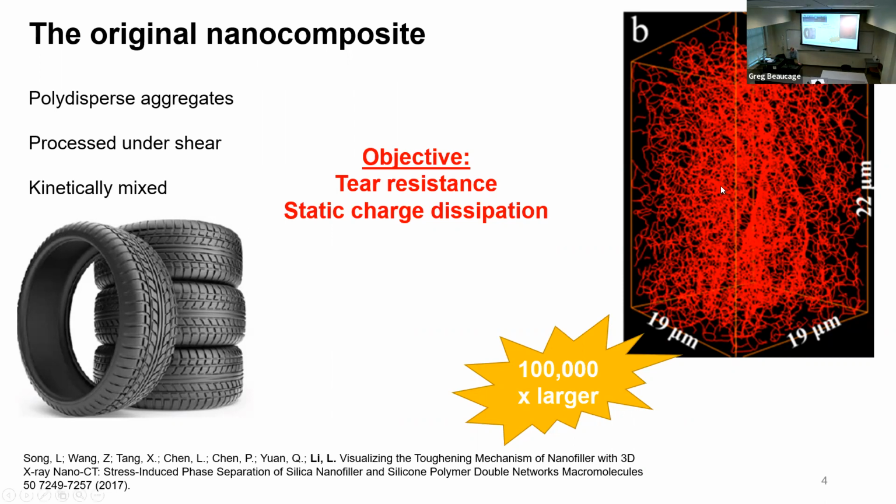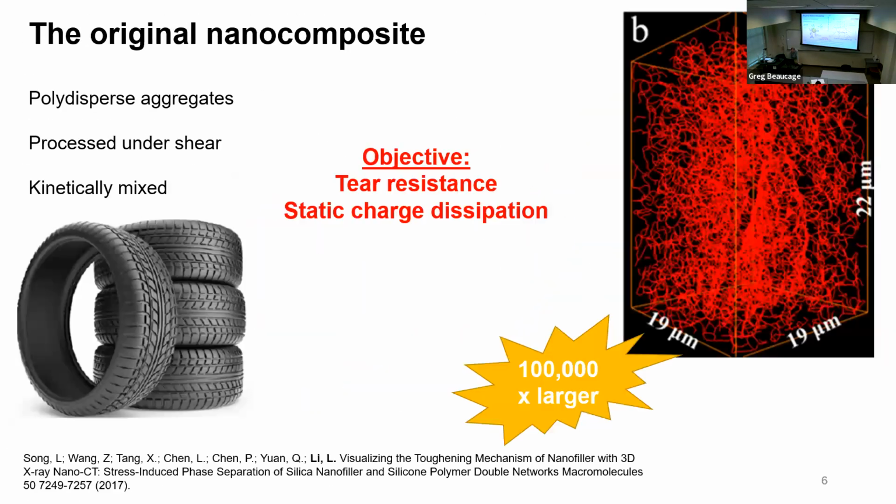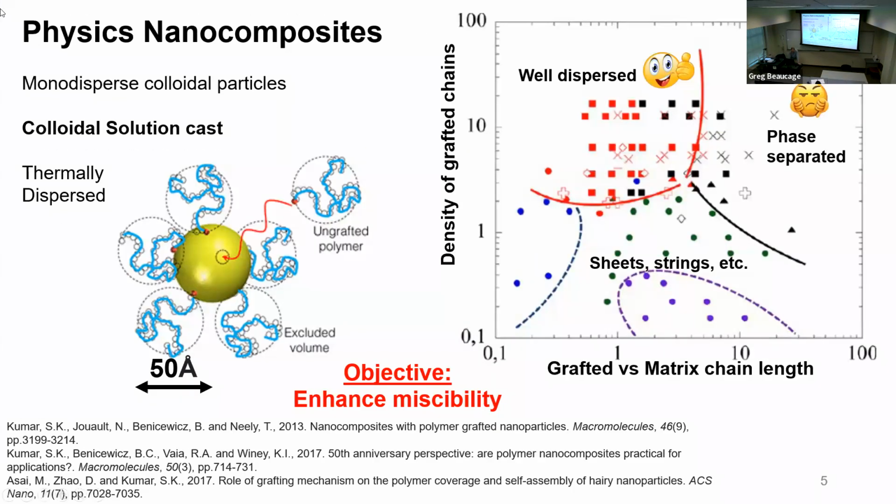So this is the kind of thing you want, you know, and this is kind of what people are doing, right? So you take a monodispersed spherical particle of silica, which you can make by a sol-gel synthesis using that same TEOS. You take that TEOS, put it into ethanol or into an ethanol-water mixture, then change the pH, and the TEOS will condense, produce water or ethanol, and then these perfect spherical particles will come out. That's called Stöber synthesis. It's been around since the 50s. So you can make perfect spherical balls.